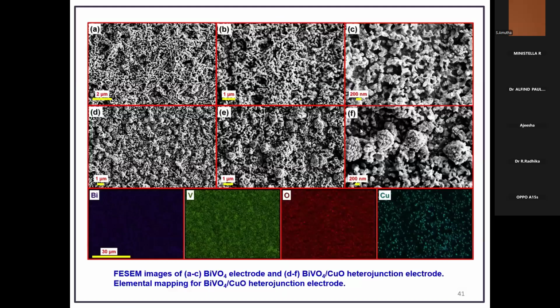Then this is the FESEM analysis. This is the bismuth vanadate electrode. This is after electrodeposition of copper oxide over the bismuth vanadate electrode. So you just look at this. This is the elemental mapping showing the presence of bismuth, vanadium, oxygen, and copper in the electrode. So this clearly confirms that it is free from impurity.